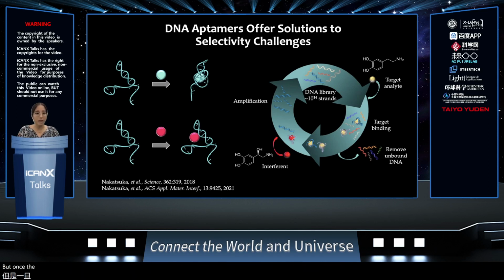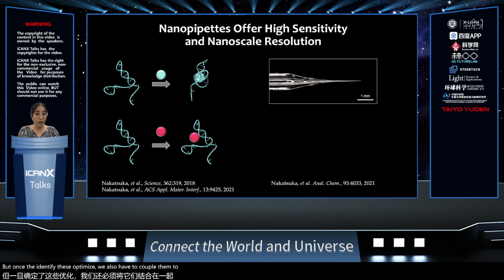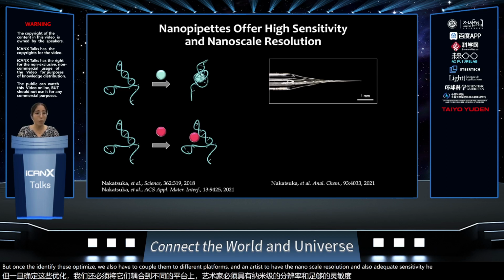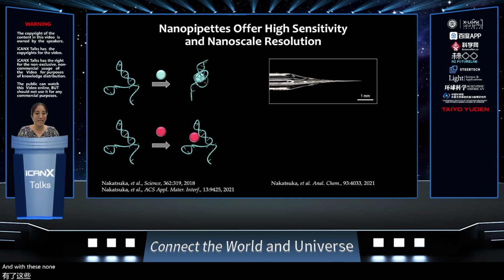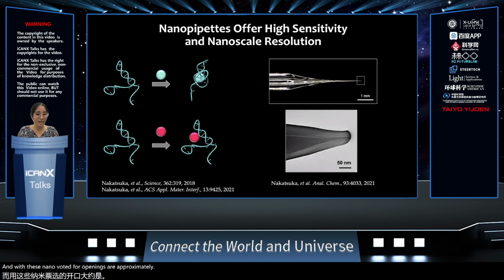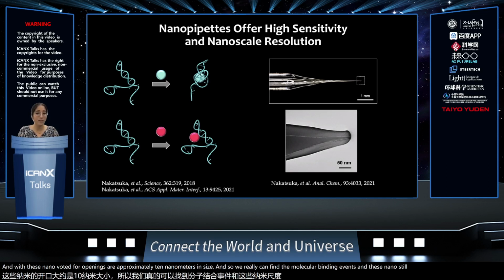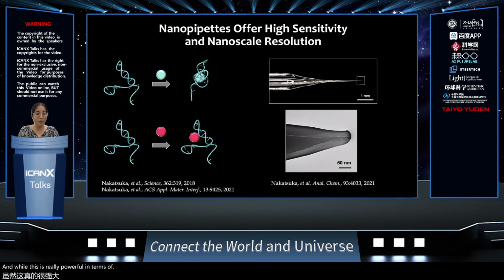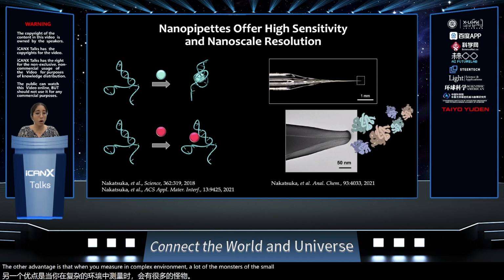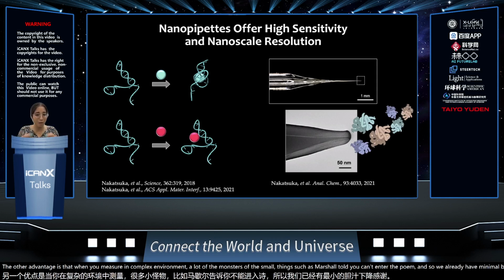But once we identify these aptamers, we also have to couple them to different platforms. And in our case, to have the nanoscale resolution and also adequate sensitivity, we work with nanopipettes. My PhD work worked with transistors, but this is a novel platform. And with these nanopipettes, these pore openings are approximately 10 nanometers in size. And so we really confine the molecular binding events in these nanoscale orifices. And while this is really powerful in terms of the confinement, the other advantage is that when you measure in complex environments, a lot of the non-specific molecules, such as larger proteins, can't enter the pore. And so we already have minimal biofouling thanks to really localizing the biosensing inside of these nanopores.